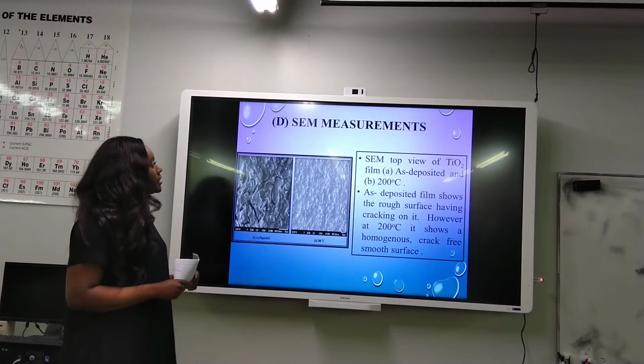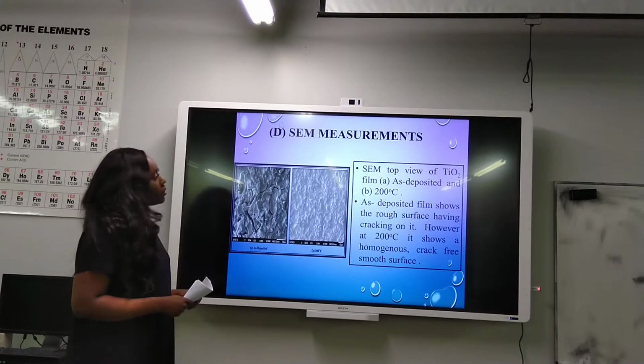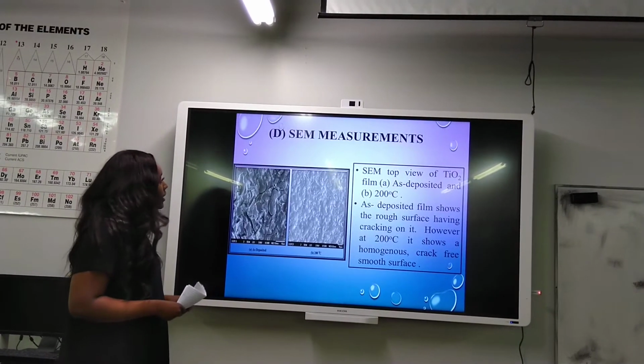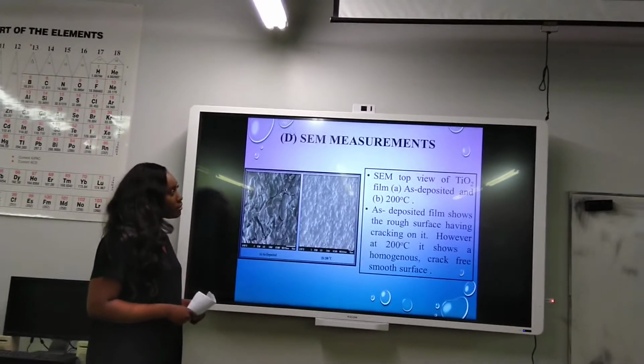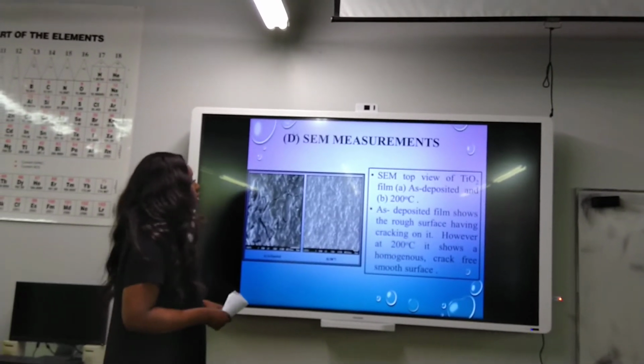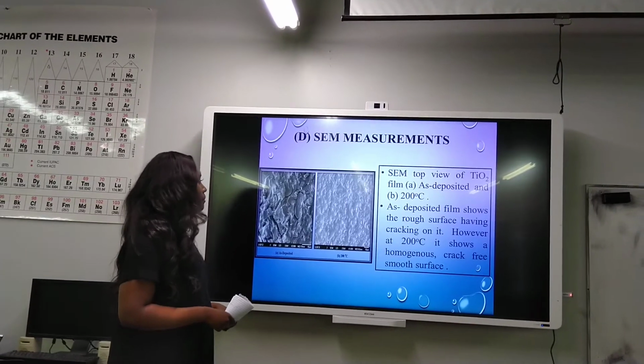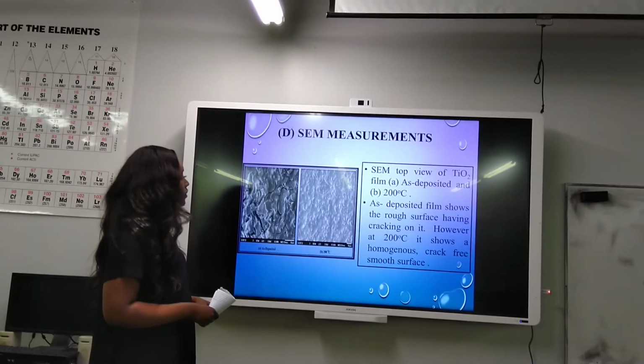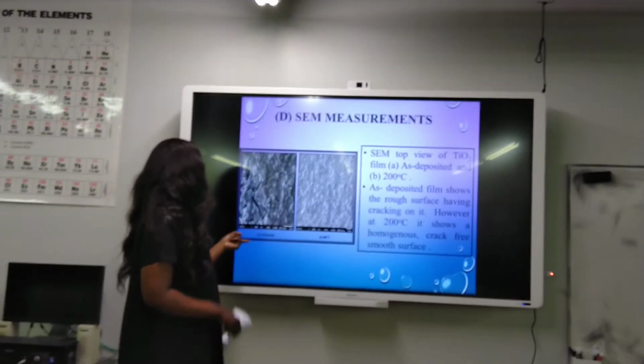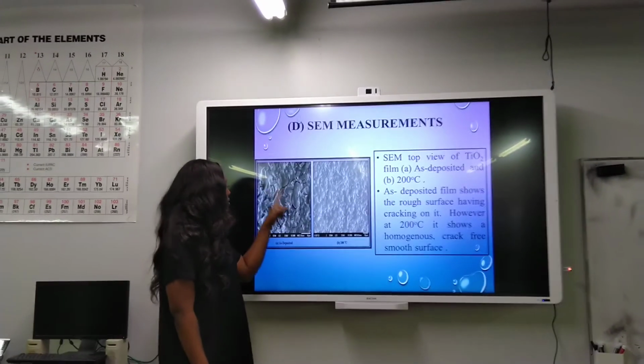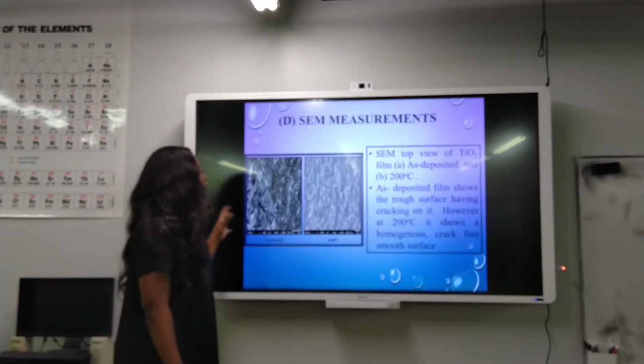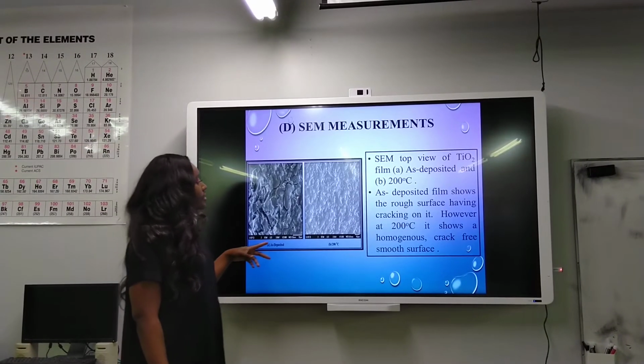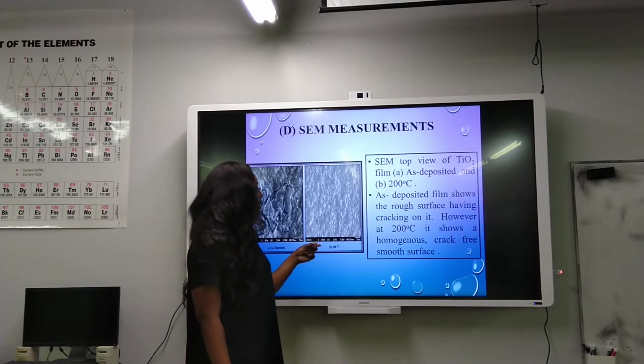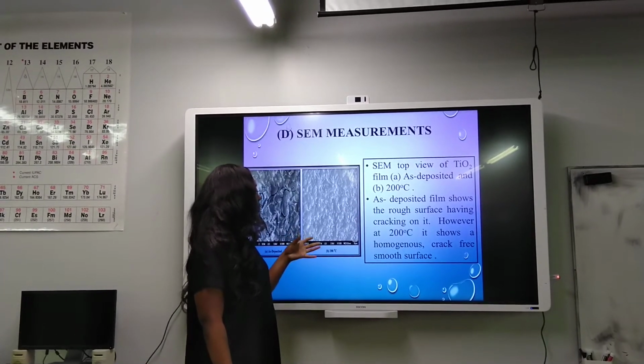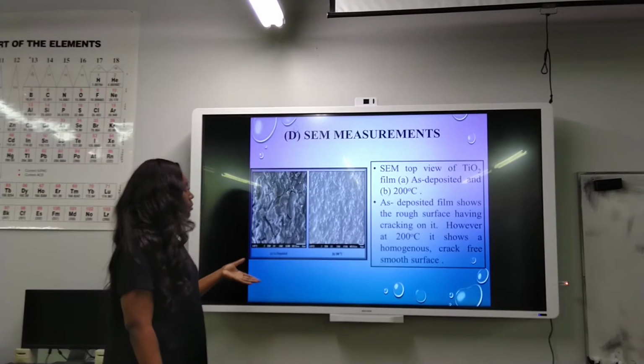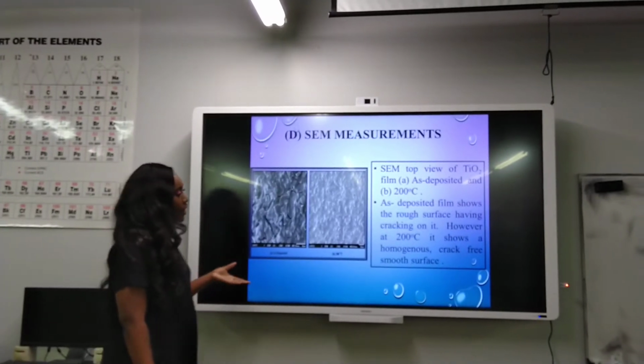So this is the SEM measurement, which is the scanning electron microscope. Okay, so this basically is the top view of the TiO2 thin film. So the first one is the as deposited film, and you can see that it's cracking and that the surface is kind of rough. And then at the 200 degrees Celsius annealing temperature, you can see more of a smooth surface, homogeneous type, and then it's crack free.